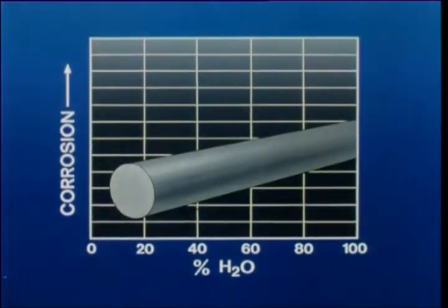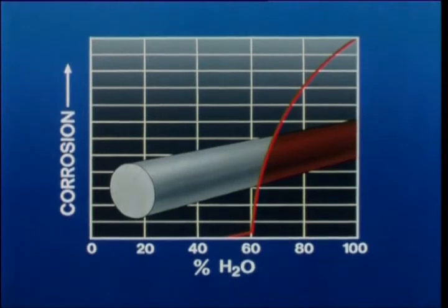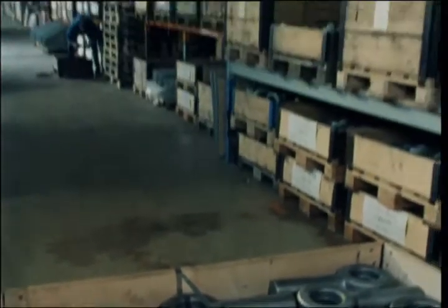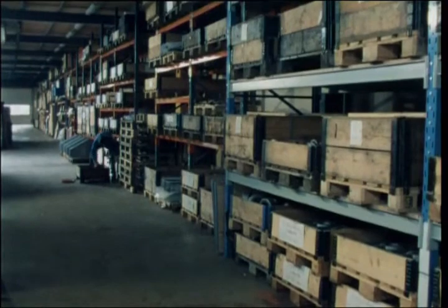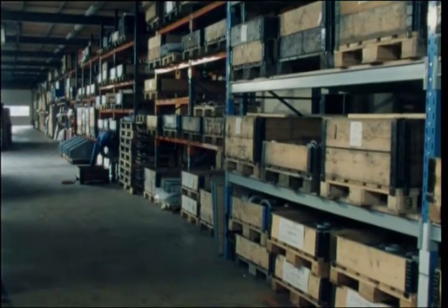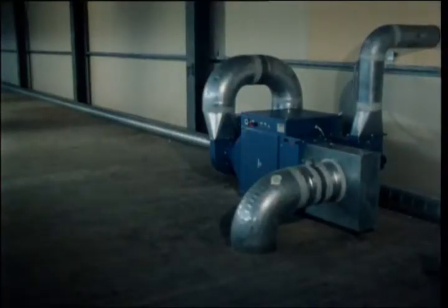Only when the moisture is above 60% relative humidity will steel rust. This has considerable use for interiors, both large and small. Here, engineering components are protected during storage by dry air blown down from the room above.